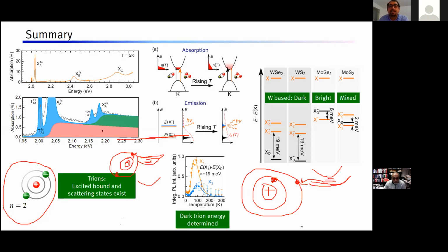So the Stark effect, normally for these bound excitons, has not been seen because of the very strong binding energies of these excitons. However, for interlayer excitons, it has recently been seen. In fact, there are 3 papers on arXiv at the moment which show that when you apply an electric field, you are able to shift the interlayer exciton resonances. In fact, you are able to create 2 interlayer exciton resonances out of 1, where the electron and hole are either in the upper layer, or the electron or hole are in the lower layer, and so on.